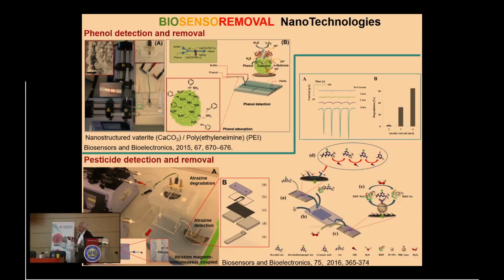We did the same, but instead of applying potential to destroy the contaminants, we use some polymeric compounds. This is a nanostructure based on vaterite, calcium carbonate, modified with polyethylenimine, where we did the detection of some compounds, but then at the same time we were absorbing these contaminants and removing them from the sample.